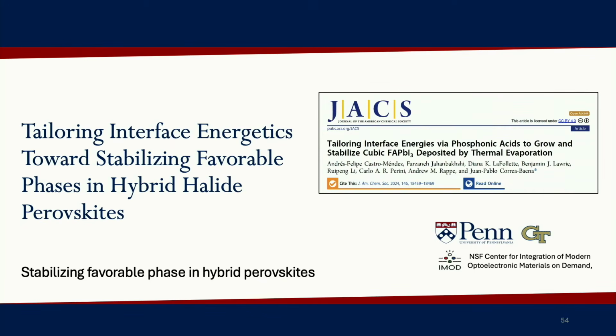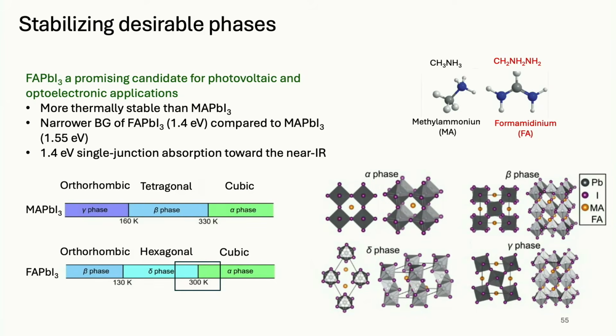All right, so again, using materials design, now instead of ligands, we're talking about molecules that chaperone growth of the phase that we want. So I spent 45 minutes talking about the perovskite phase. Well, the material that some of my friends want to make is formamidinium lead iodide. But look at the phase diagram. It likes to make these other phases. And unfortunately, there's this phase, do you see it's not even corner sharing octahedra? Because they're not connected, it's not going to be good for electron and hole transport. It's not a good photovoltaic material. It's made of exactly the same stuff, but it seems to be favored. So that's very sad.